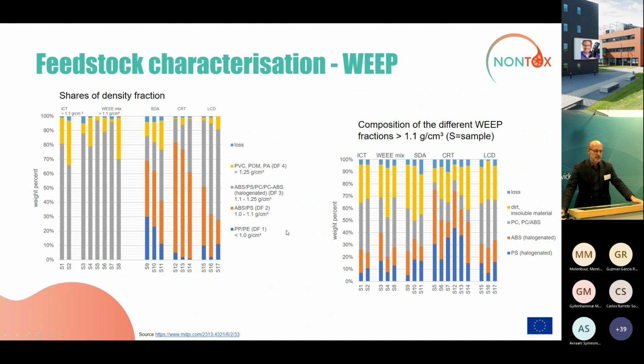Below 1.1 we have smaller shares of this one. We have then some shares of the ABS, PS in the below 1.1 density fraction, and we have some in the higher fractions. Depending on the source, it makes sense to go only for these intermediate fractions in the PE, PP, ABS, and PS, which is here in the range blue and orange, which is a nice yield and which is more or less currently state of the art to make use of it.